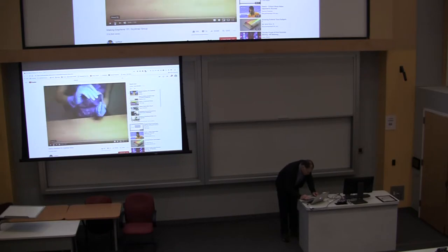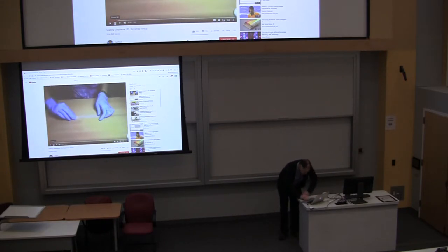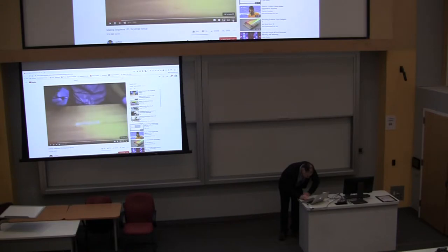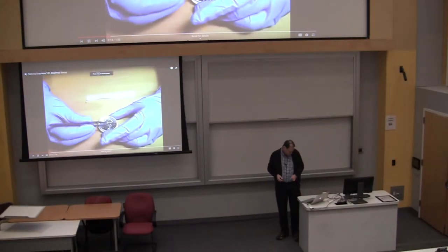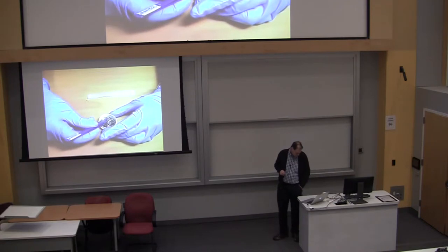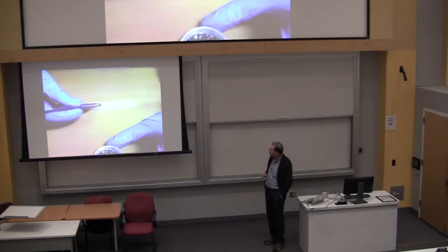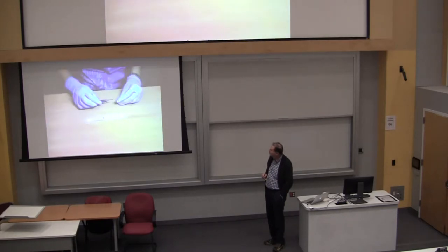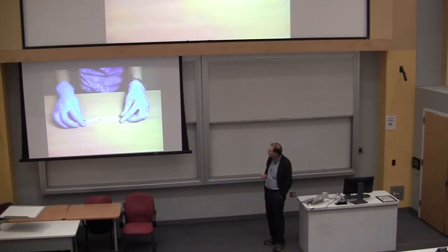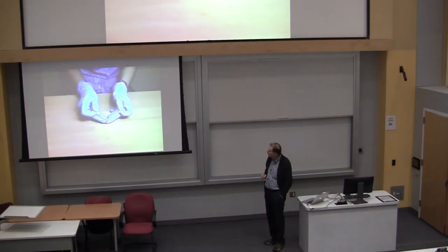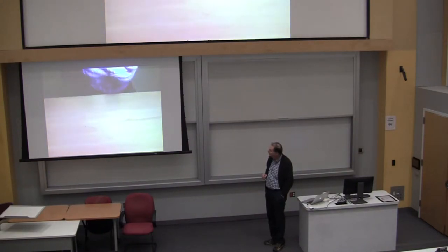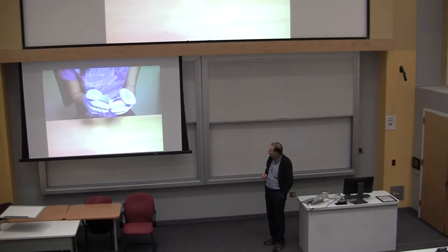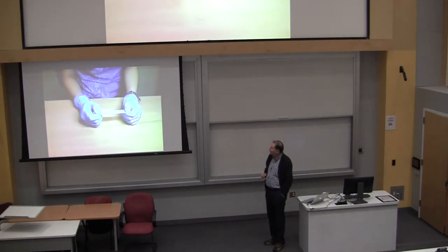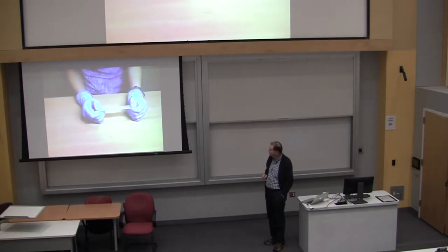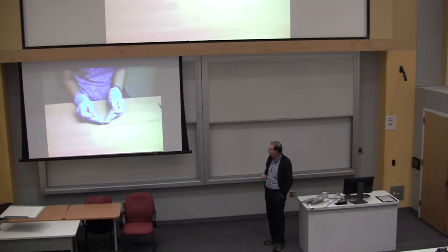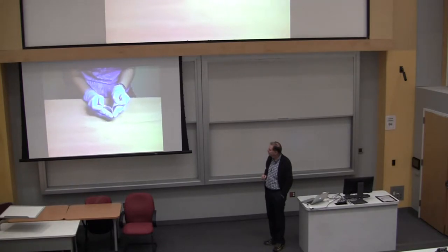Take a scotch tape and gently lay it down on a flat surface. Next, take clean metal tweezers and pick a thin graphite flake and then place this gently onto the scotch tape. Next, fold the scotch tape at the edge of the graphite flake. Peel it off gently, and do this step several times until you obtain a nearly transparent region on the scotch tape.